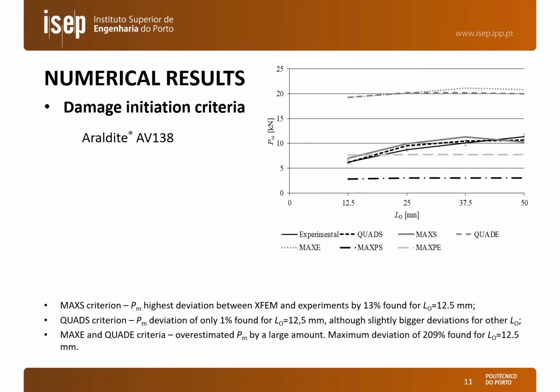Regarding the numerical results, we present initially the results for the Araldite AV138, in which we compare the experimental results with the 6 different criteria for damage initiation. We can see that the best results were obtained by the quad S and max S criteria, and here for the max S criterion the highest deviation was 13%. For the quad S criteria we had a deviation of only 1% for an overlap length of 12.5, but bigger deviations for the other overlaps.